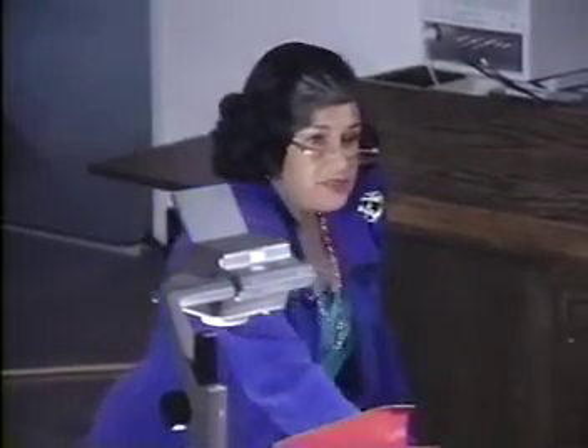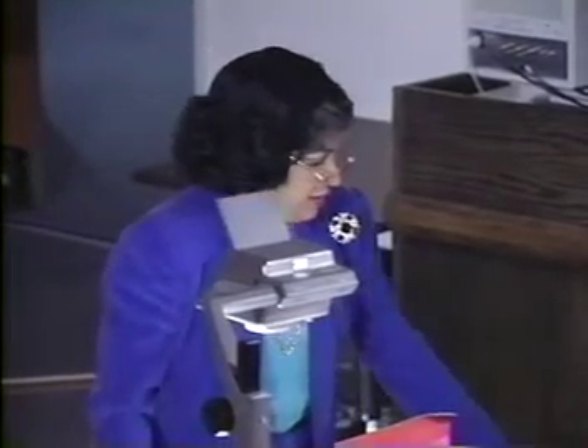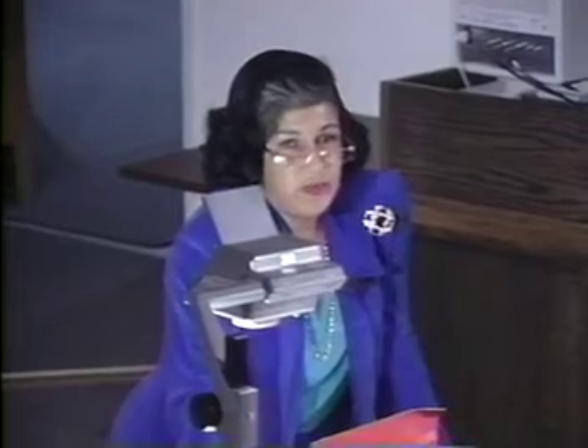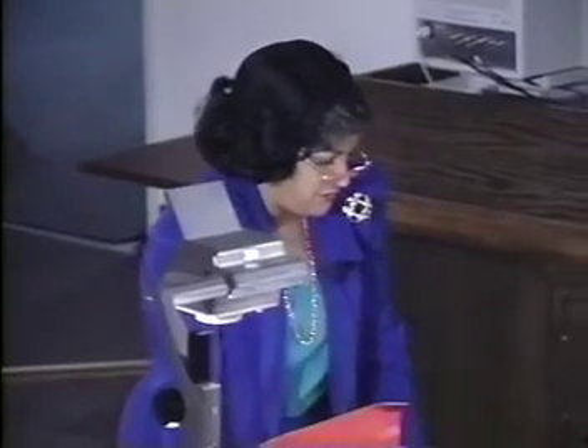Some of the factors that affect this process are the properties, of course, of the metal. If you had a piece of glass and you put a punch in it, glass is a ceramic, it would break. If you had a piece of very brittle material, say, very high strength aluminum with very little ductility, and you put this punch in it, again, instead of stretching, we would induce cracks and failure. Okay, so the properties of the sheet metal.